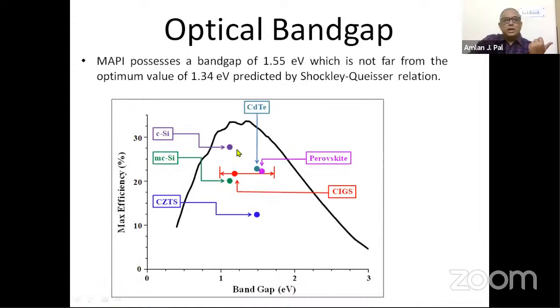This is silicon, as I have said, that it can really go up to 32 or 33% efficiency, because that is its band gap. And then CIGS or CdTe, these are the materials that lie within this range, so the values can be high. And the perovskite is somewhere here, 1.55. So it can really go up to nearly 30% or 28%. So that is the highest value it can theoretically achieve.